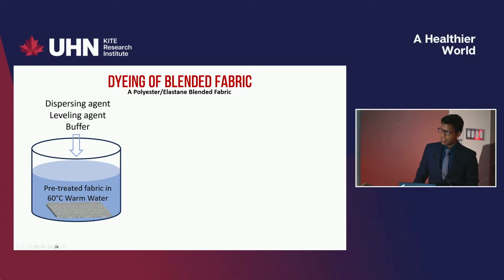In the dyeing preparation, as from the previous steps, we have already pre-treated fabric at 60 degrees centigrade warm temperature. Then in the same water, we include two more agents, dispersing agent, because here in this case of polyester, the dye we can use is called dispersed dye. It doesn't bond easily with the polyester, so we want to disperse the dyes as fine as possible with the help of dispersing agent, and the leveling agent helps us for the even dyeing. And then we include the buffer solution to control the pH of the water.